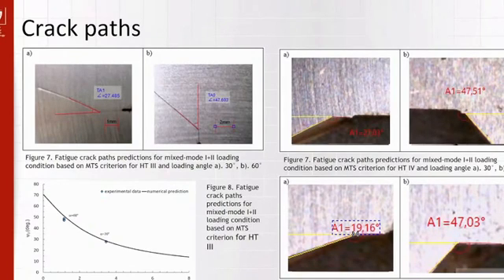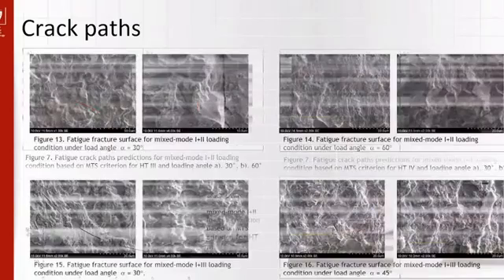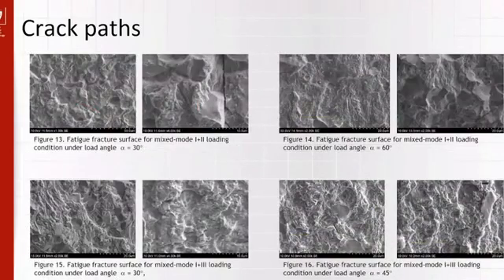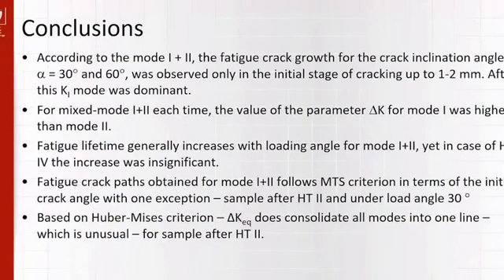So just quickly here you can see that for most of the cases, the MTS criterion is fulfilled. Let me skip through the SEM samples, and in the conclusions, I can simply say that for mode 1+2, the fatigue crack growth for the crack inclinations 30 and 60 degrees was observed only in the initial stage.